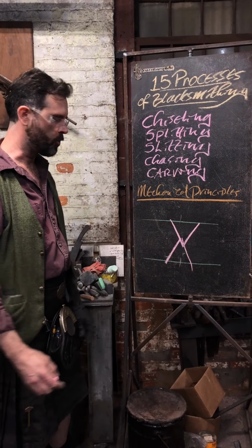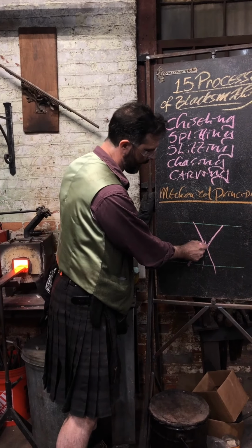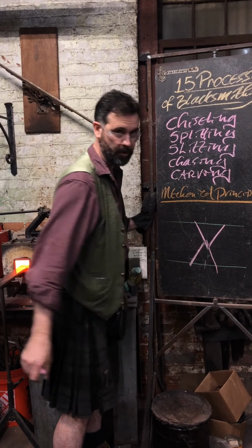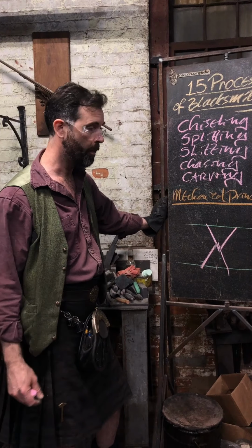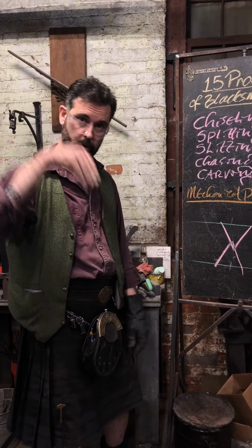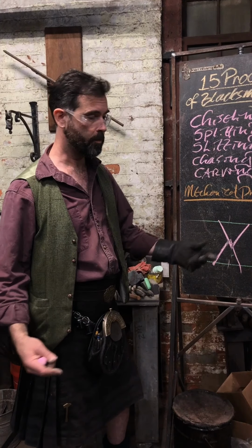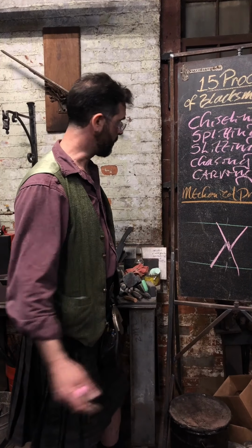And what happens is you wind up with this weird little rag bit in the middle, and when it does split, this section here has to be peeled out. So you then have to do a secondary cut to peel that out. But sometimes that's the only way, because the material's just too damn thick to come through from one side. So in much the same manner as when we were doing the punching stuff the other day, which I will have to revisit.